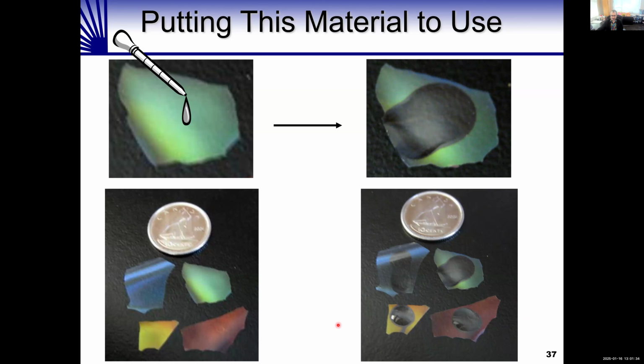In fact, because this is structural color, these materials can keep their color even if you heat them at 500 degrees in air for days. They will not lose their color—they will never fade. I've had samples of these on my desk for over 10 years, and they look exactly the same as when we made them. You could shine lasers on them, and because they don't absorb light, only reflect it, they won't undergo any optical damage. So there are lots of interesting applications for these materials.